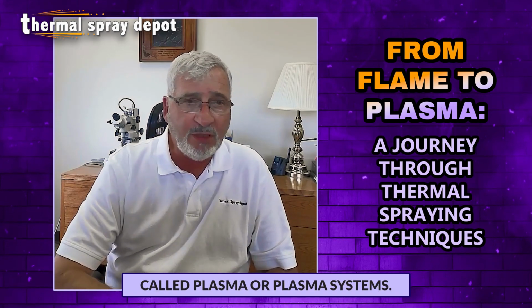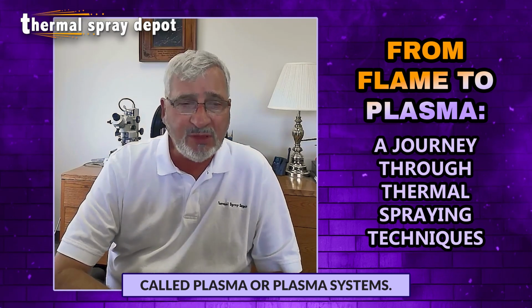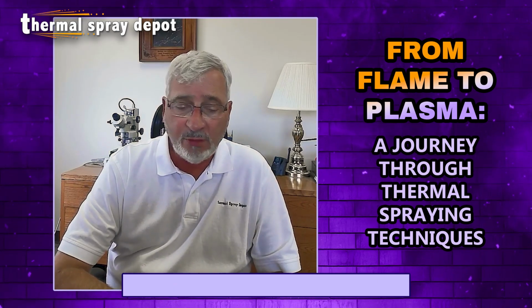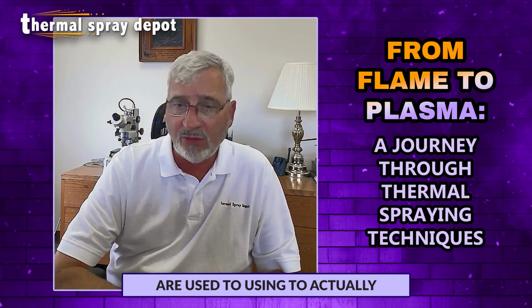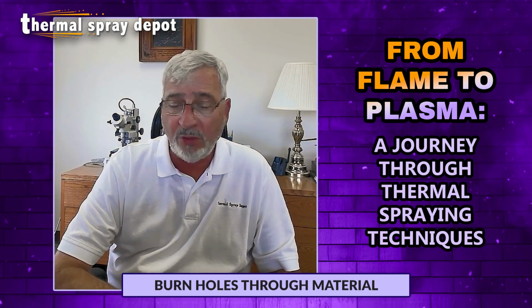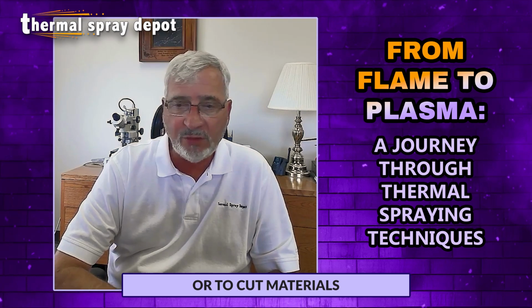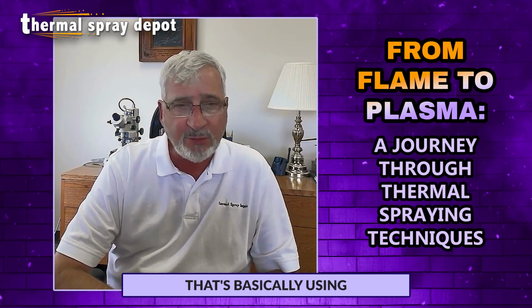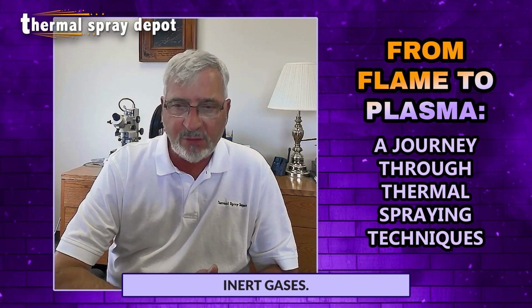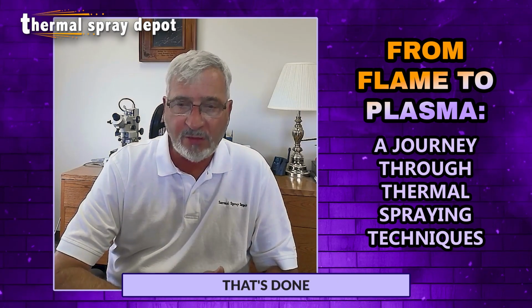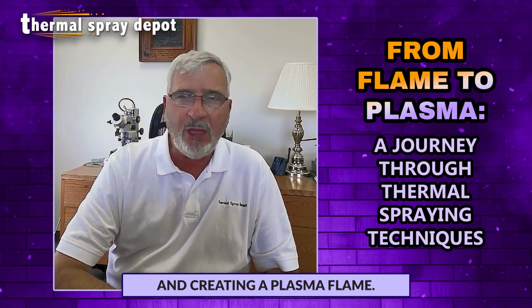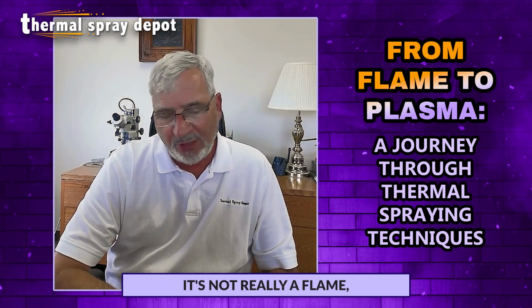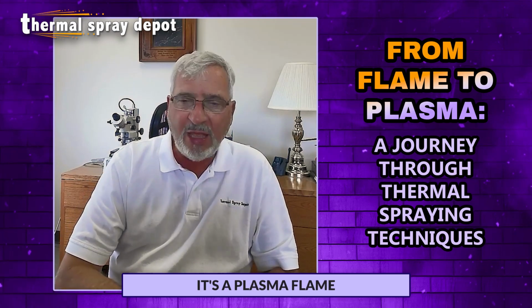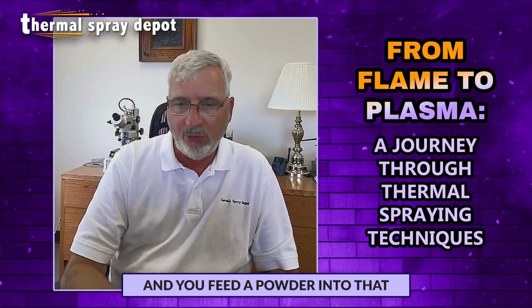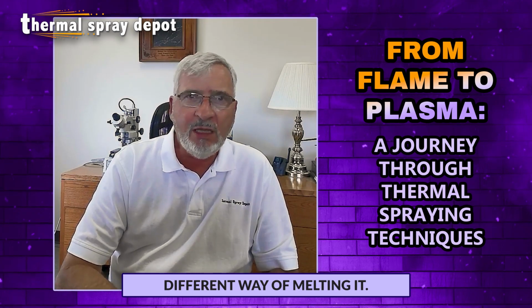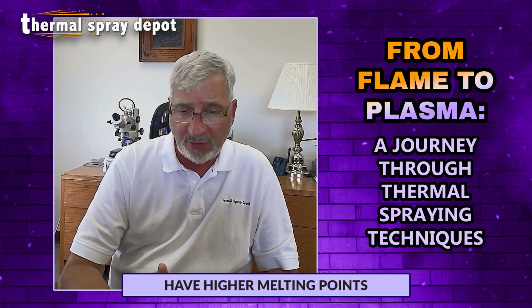Then we step up to something called plasma, where plasma systems use a plasma arc, very similar to the plasma arc that welders are used to using to burn holes through material or to cut materials using that plasma arc torch. That's basically using inert gases, running them through an arc and creating a plasma flame. It's not really a flame, but that's what everybody calls it. It's a plasma flame of high energy. And you feed a powder into that and melt it. Different way of melting it. Works really well with ceramics because ceramics have higher melting points.